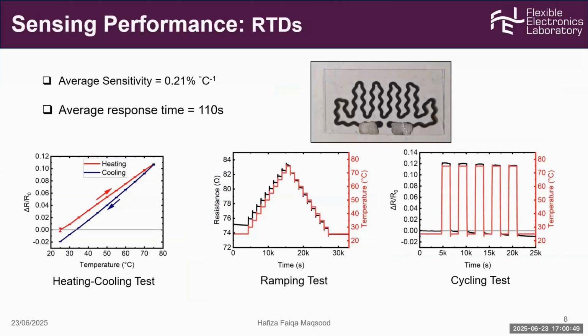The electrical characterization was performed by using a custom designed setup. First, we performed a heating cooling test where we continuously increased temperature from 25 to 75 degrees, and a linear trend is reported between the resistance and the temperature.